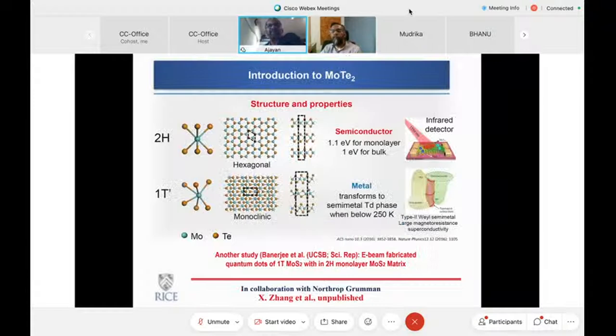A very different type of system is a composition, molybdenum ditelluride. Here, similar kinds of 2D engineered structures could be made, but with the same composition. When I say same composition, the way you can make these metallic and semiconducting junctions is by choosing the phase that you use. Molybdenum telluride exists as 2H and 1T prime phases, just like I mentioned before. If you can coax them into these patterns that I showed you for the BCN structure, you could create some very interesting metal semiconductor junctions within a single unit thickness.